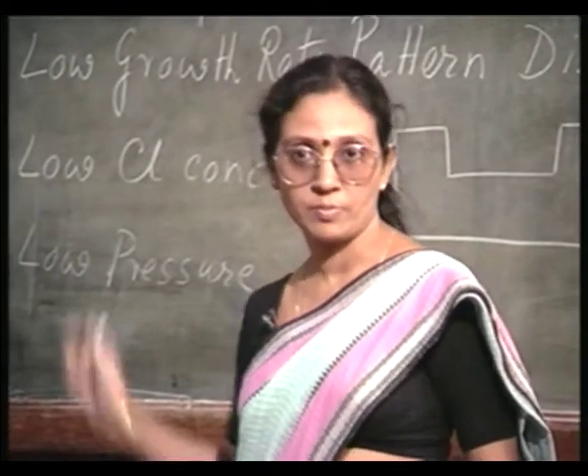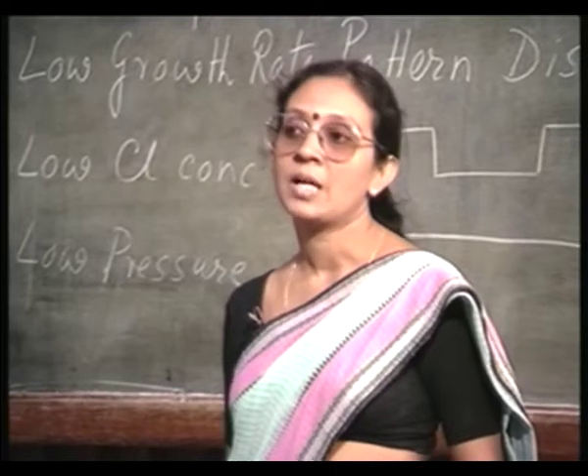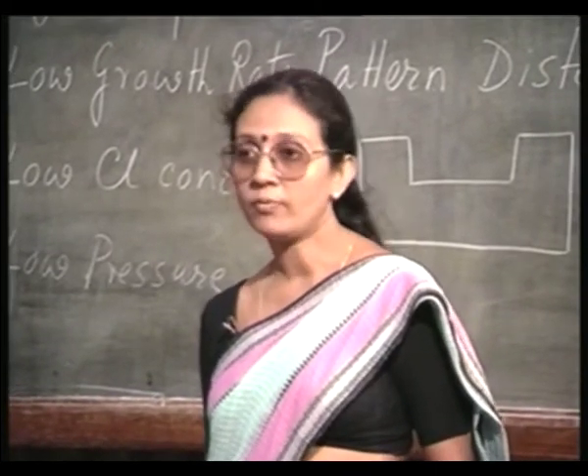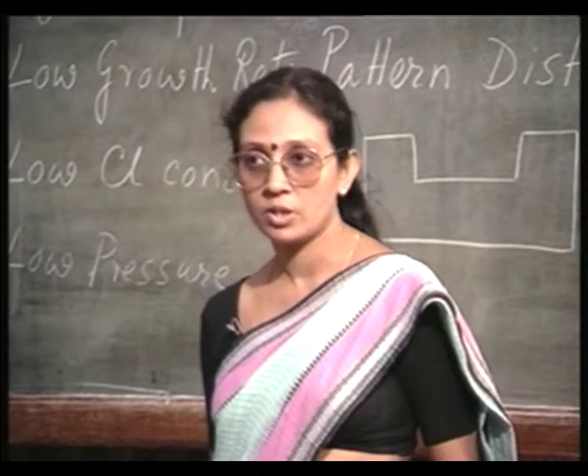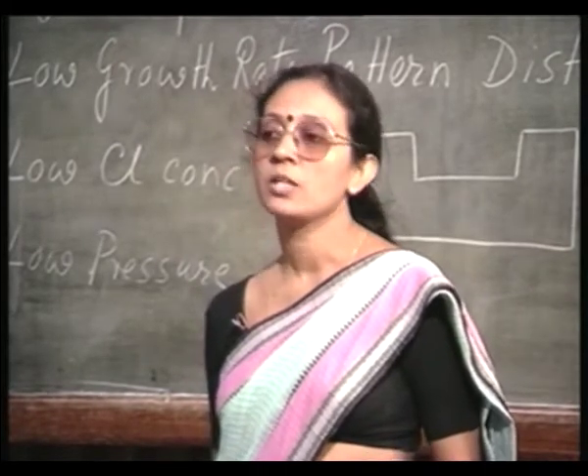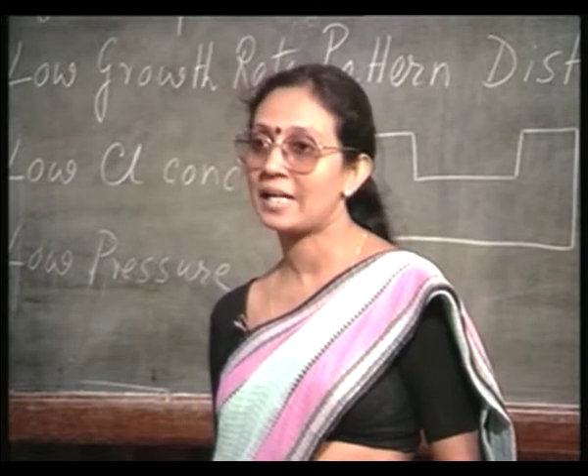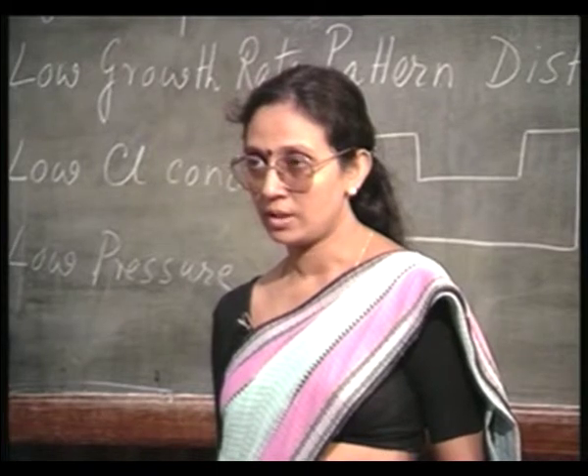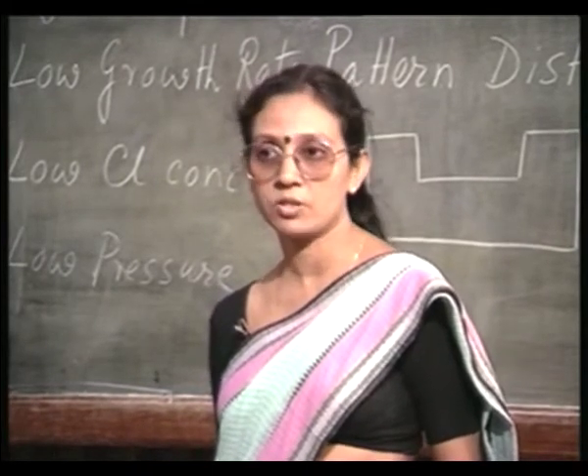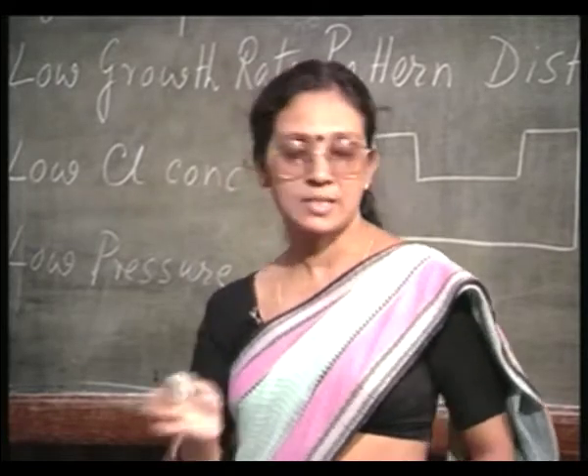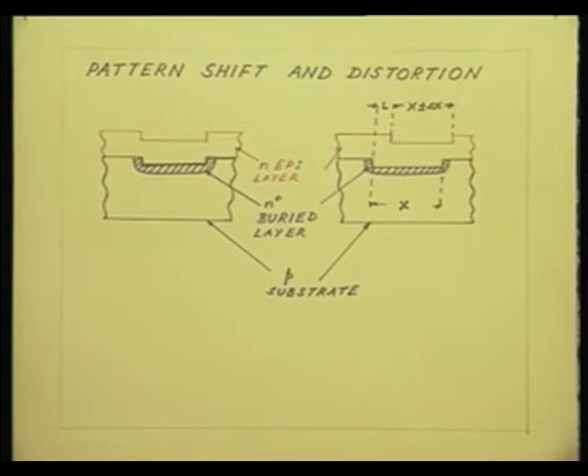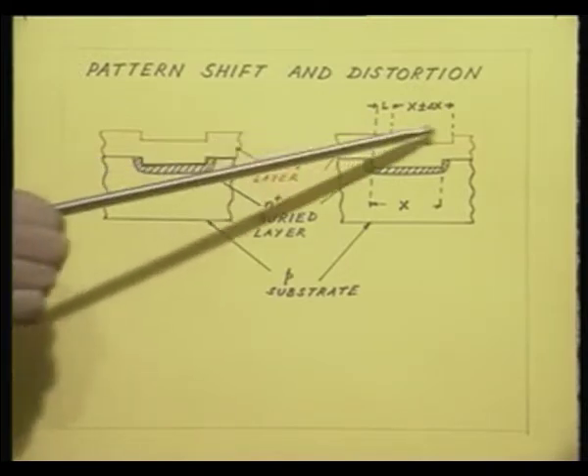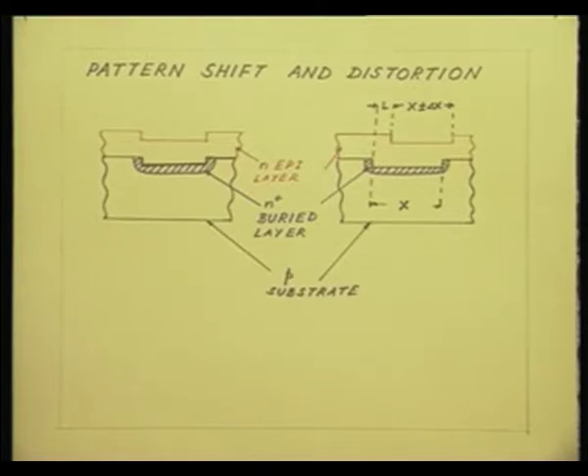So, one aspect is that we have to minimize the pattern shift by carefully controlling the process parameters. The other aspect is, in spite of all these precautions, if you have pattern shift and pattern distortion, then your subsequent masking steps should take care of this defect. That is, you must be able to identify how much pattern shift there will be. So, even if the step gets shifted by an amount L in this direction, then your next mask should actually be shifted in a direction minus L, in order to take care of the alignment problem. Okay?